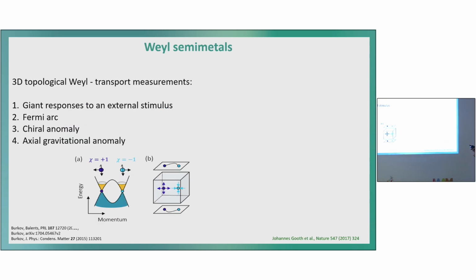So therefore, if we make a Weyl semimetal, we try to look for different features which are related to the chiral anomaly, which are then translated by Burkov and Balents, for example, into measurements or features in a solid. The proposal was that we see giant responses to external stimuli. We see these Fermi arcs, which I already explained before, but we see also this chiral anomaly.